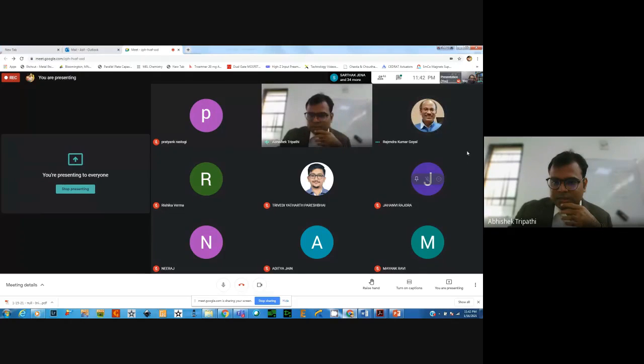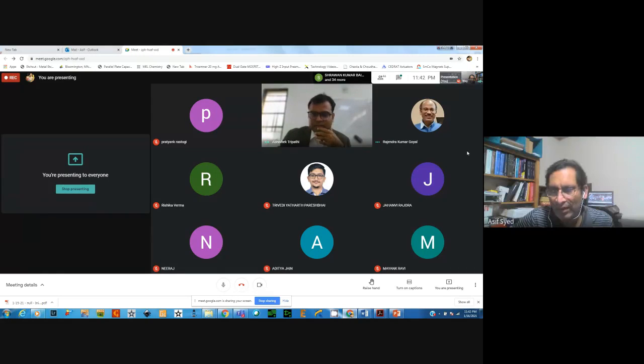Himanshu is asking, as we could see the dislocations disappeared, where exactly do they disappear to? Do they accumulate on the surface or do they vanish completely? I think it goes to the surface. It creates a step. When the dislocation disappears at the surface, it will create a step, a Burgers step, whatever that is. Okay.